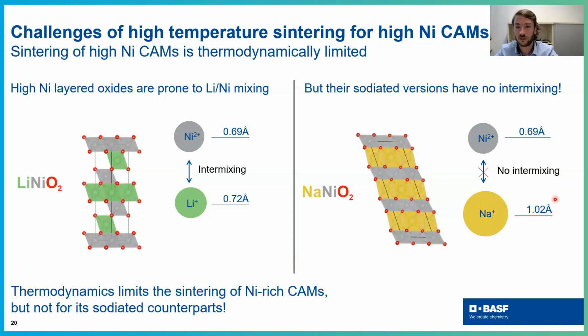Here the idea was that we start from sodium nickel oxide, where you have very large sodium ions and just your nickel, right? And they just do not intermix. And this is what we did.